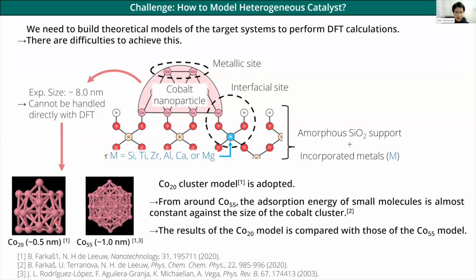Yeah, right. In this calculation, I just used the simple RPBE without any van der Waals correction. But before performing this calculation, I checked the accuracy of RPBE and RPBE with van der Waals correction. For this, I adopted the Tkatchenko-Scheffler type van der Waals correction. I investigated the adsorption energy of carbon monoxide on the cobalt surface, because there are experimental reports for the adsorption energy and the vibrational frequency of CO on the surface. I realized that, as other people mentioned, van der Waals interaction is very good for representing the physisorption of molecules on a metal surface.